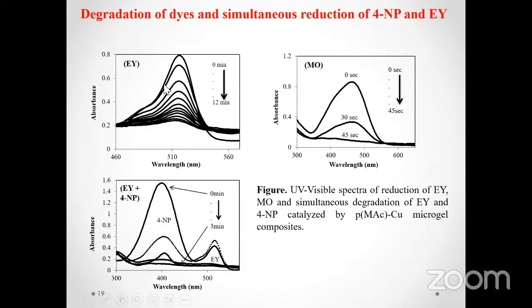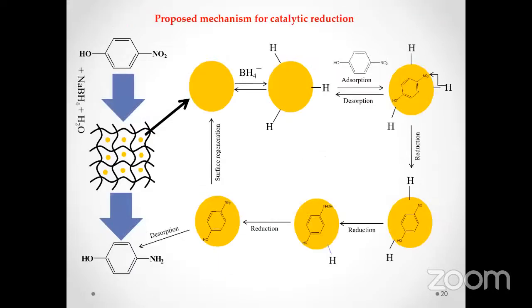Catalytic potential was also observed for some other water pollutants, which are dyes, and we have considered both the cationic and anionic dyes. Here is the catalytic reduction of eosin Y and methyl orange, and then it was also observed that this catalyst can also act simultaneously if we have multiple reactants in the same reaction medium. So by using this catalyst, we can degrade multiple water pollutants present in the same reaction mixture.